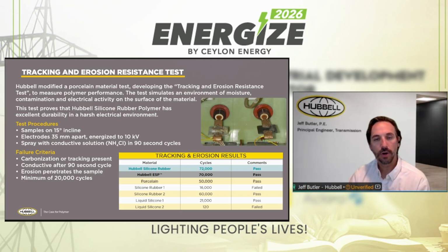And now the cycles are, you're taking a plaque, you're placing it between two electrodes that are energized at 10 kV, 35 millimeters apart, and then you're cycling a conductive solution being sprayed on it every 90 seconds. And so that is a cycle. So you want it to at least pass 20,000 cycles.